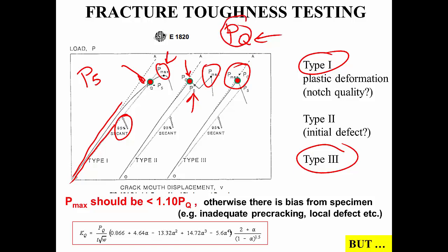In any event, we take that value of the load and we put it in the formula for fracture toughness. This is a slightly unusual way of writing the equation, but it doesn't really matter. So you have the load here. I believe T is the thickness, W is the width of the specimen, and alpha is actually the crack size. You calculate your fracture toughness, but this is really not fracture toughness.